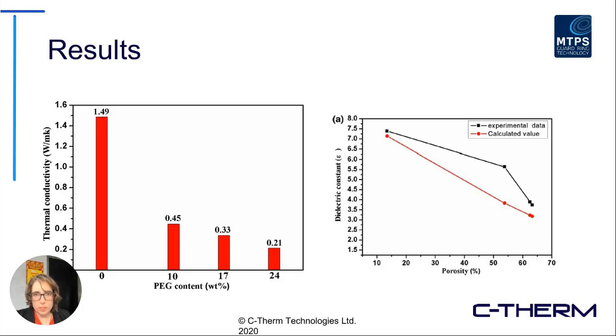And the results on this are seen on the left-hand side for the thermal conductivity and the right-hand side for the dielectric constant. And you can see that for thermal conductivity, as porosity increases, the PEG content is the pore-forming agent that was used. So as that goes up, so too does porosity. So as the PEG content increases, thermal conductivity decreases, which is as you would expect. Of course, as porosity increases, thermal conductivity usually will decrease in a porous material. And then on the right-hand side, you can see the same trend is observed with regards to dielectric constant, which should also aid in the performance of these materials.